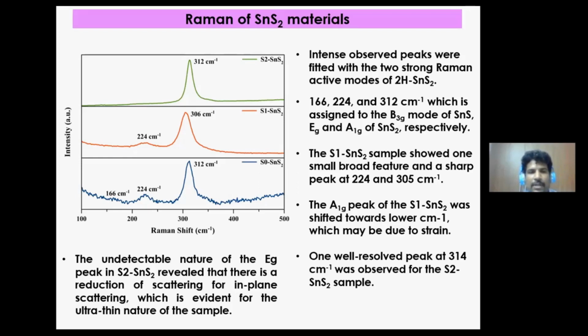With this Raman, we can conclude that S2 SnS2 shows only 1 peak, so that it predicts that the synthesized material is 2-dimensional. Okay. In the S1 SnS2 sample, we can observe two modes, EG and A1G modes. So with this, the sample is somewhat 3-dimensional. Okay. And also there is a shift in S1 SnS2. Usually the A1G mode of SnS2 arises at 312 centimeter inverse to 314 centimeter inverse. But in our case, S1 SnS2 shows a shift to lower centimeter inverse. So there is a reduction of scattering.